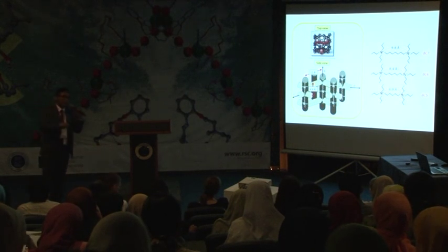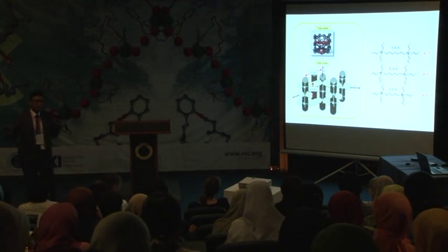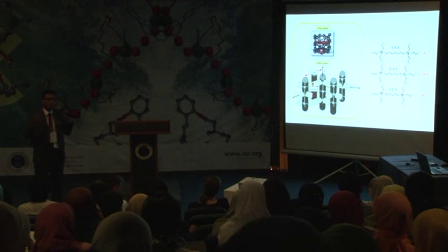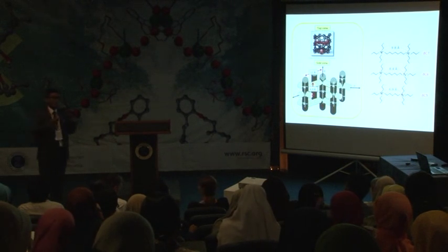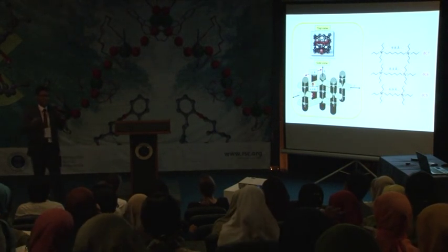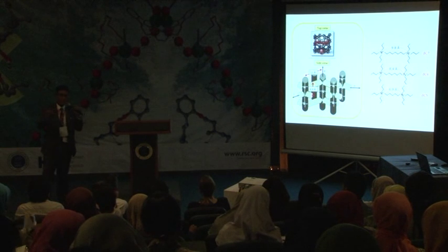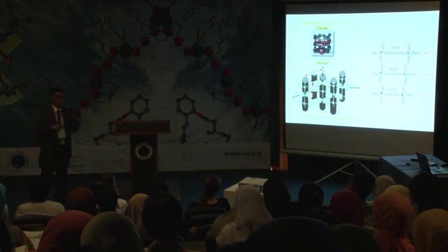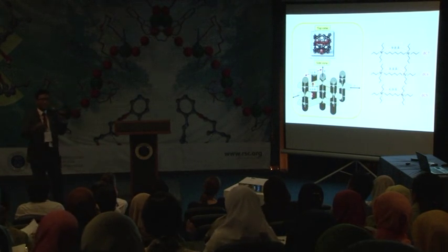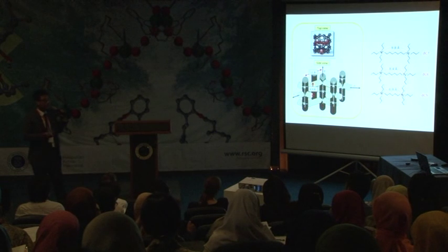We learned from the Nature paper, because they were using very long surfactants, about 22 carbon chains. So it's too much. That's why they can make nanosheet. So only some part of the carbon can mediate the formation of the framework of zeolite. But we were thinking the other way around. We just want to use as small as possible the structure directing agent, the organic molecules.